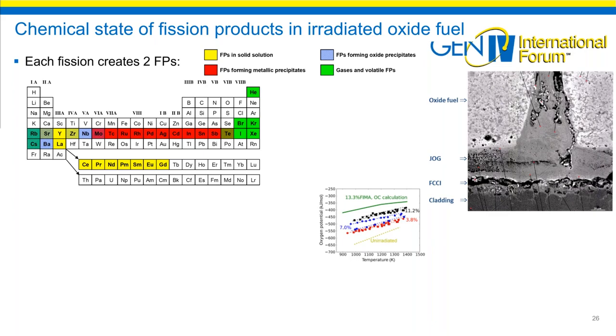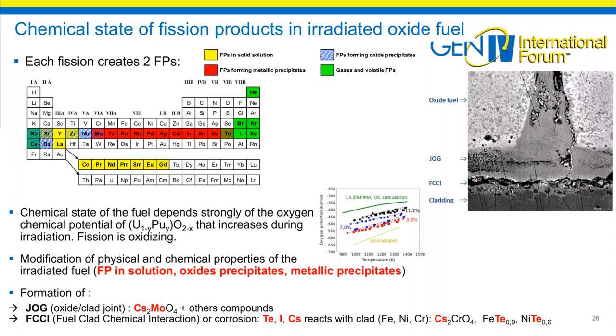So the chemical state of the fuel depends strongly on the oxygen chemical potential of the MOX fuel, and it increases during the irradiation. We have seen that the fission is oxidizing. As you can see here, the oxygen potential is increasing with the burn up from the yellow status after the fabrication until the green curve after 13 atom percent.